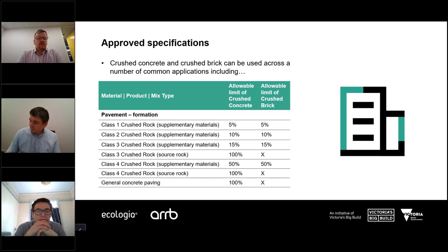And this table highlights the current Department of Transport Victoria guidelines. So the class 1 crushed rock that I spoke of earlier that you couldn't use crushed concrete in, you could actually have up to 5% of that material being crushed concrete if you so wished as a supplementary material. However, if you look midway through that table, you see class 3 crushed rock, source rock, that could be 100% crushed concrete. And that's the example I was talking about in the rural pavement. And you can see similarly, brick can be used in small percentages in class 1 material and in increasing percentages up to 50% of a class 4 material could be composed of crushed brick. So there's definitely a use for these engineering materials in our new road construction.